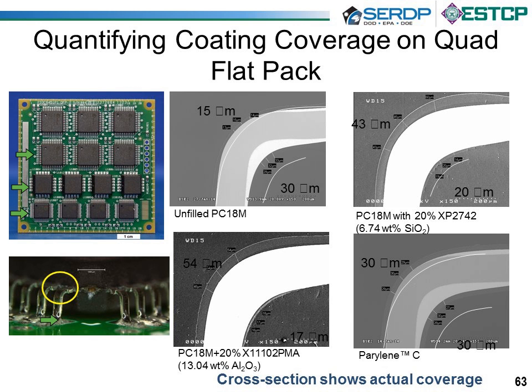The reason cross-sectioning was necessary was that we needed to actually quantify the coating thickness. So along the top of the knee, it was thinner than on the back in this particular case. That's interesting because the coating wrapped around this particular lead and coated behind there. So that was very encouraging. With the nanosilica, we had better coverage on top and behind, so that was good. And on the nanoalumina, we had excellent coverage on the front and maybe got a little bit thinner behind.